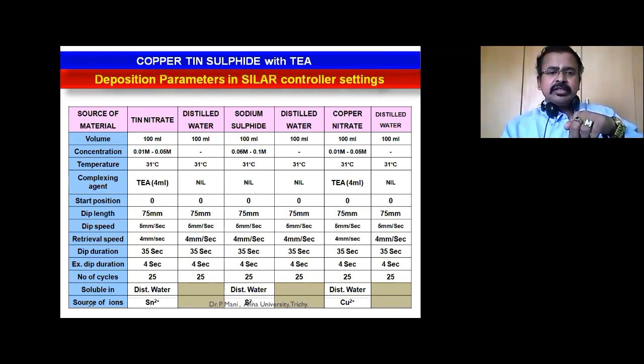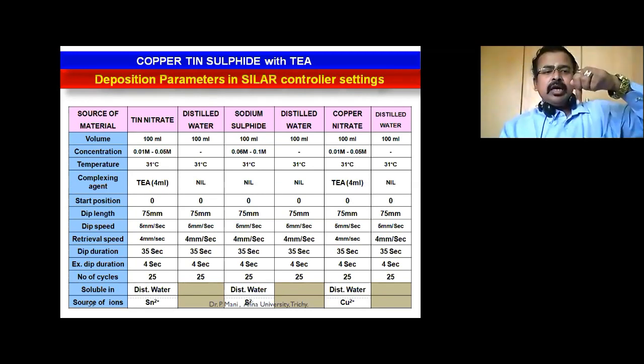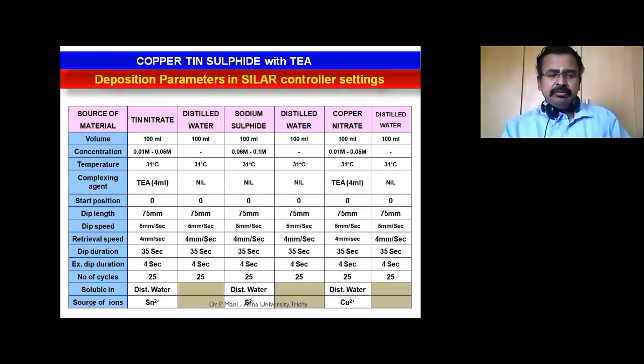The glass plate is immersed in the beaker. Ex. dip duration, that is outside the beaker, just above the liquid, is 4 seconds. The same cycle is repeated for 25 times, and it's soluble in water, right? These are the deposition parameters in the SILAR controller.